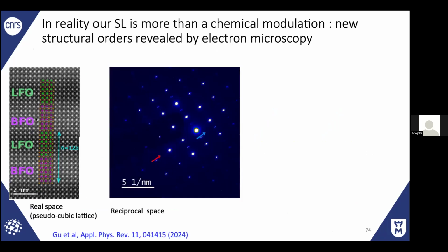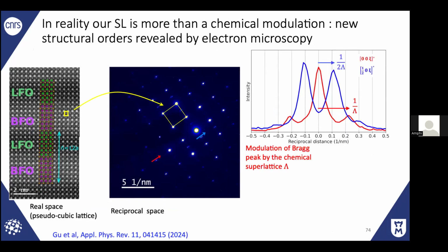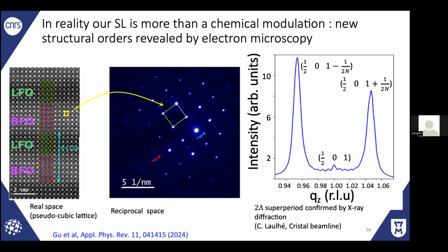So by looking at the structure, this is the electron diffraction image. So in the Fourier domain, it's the reciprocal space. This is the Fourier transform of the unit cell. But if you look, there are super orders here at a given point in the Brillouin zone. And that shows you that there is a super order. It means finally it's not A, B, A, B, it's A prime, B, A, B, A prime. So there is a doubling of the supercells. And this has quite a consequence.